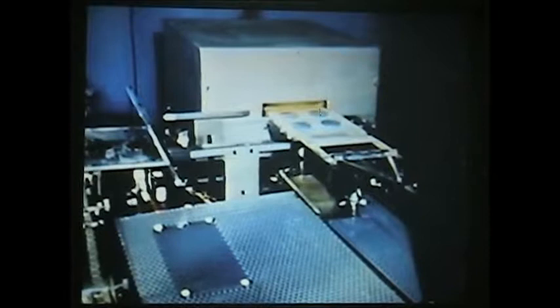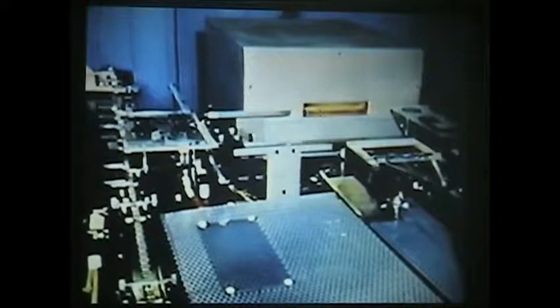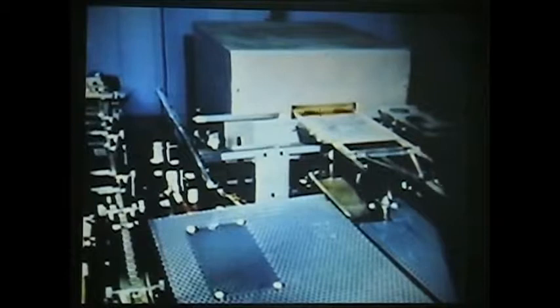And this is a mini furnace. We jack up the electricity, it goes into the furnace, and immediately reaches the steady state temperature for the wafer. The oxidation time is about a half hour, so we can change the temperature as well as the oxidation time very quickly to suit different part number requirements. Now the second boat of fresh wafers is coming in.